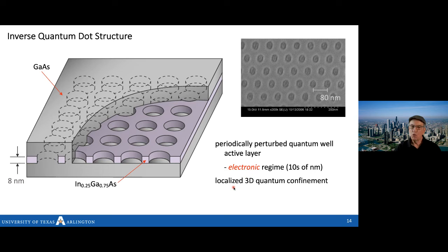This introduces localized 3D confinement, and the way to view that is to say that the carriers will live in the solid purple material, but they'll stay most localized in the regions that are farthest from the high energy material, above or in the pores. So if you were to calculate the carrier density in there, graphically, it would look something like this, where red is the highest density of carriers, and blue is a lower density of carriers, but not zero. And that's the key to where this is going.